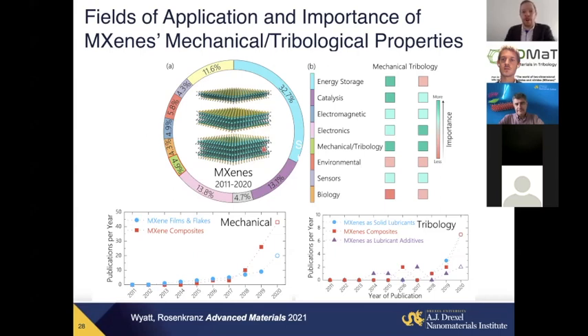Next question, is there a relationship between the number of layers and capacitance of MXenes? Well, it's not surprising there are so many questions about energy storage, because at the moment about a quarter, if not a third, of all publications on MXene are on electrochemical applications. It depends. If you completely exfoliate the material, open the structure, then again, ions can access all the surface, as we discussed with gas molecules. When MXene flakes are stacked, it may be impossible for some of the ions, larger ions, for example, or ions solvated with solvent, to access the space in between. So there is a dependence, but it's not a simple dependence where I can tell you this is better or that is better. Lithium ions, protons can go even between the layers of a stacked MXene structure, but say a large organic ion won't be able to do it.